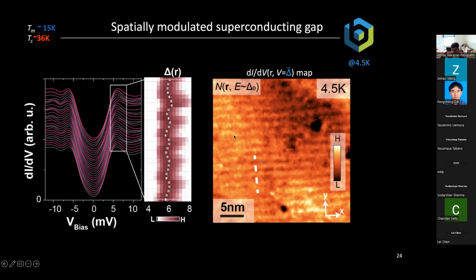There's always a gap. Instead, the formula that would accurately describe this is something like a constant delta 0 plus delta 1 times cosine of QR. That would be a formula that fits this. And something that we noticed that was very interesting is that these stripes are unidirectional. This material as a whole has 4-fold rotational symmetry, but these stripes that we observe break that 4-fold rotational symmetry, and therefore we call this a smectic, after the liquid crystal language. So it's something that breaks the intrinsic rotational symmetry of the crystal.